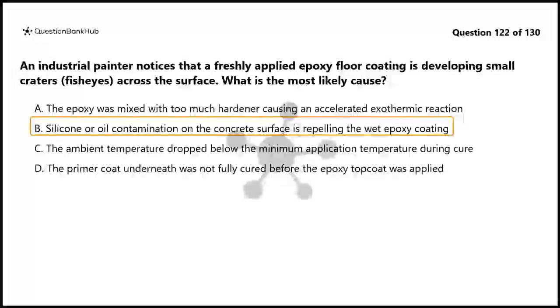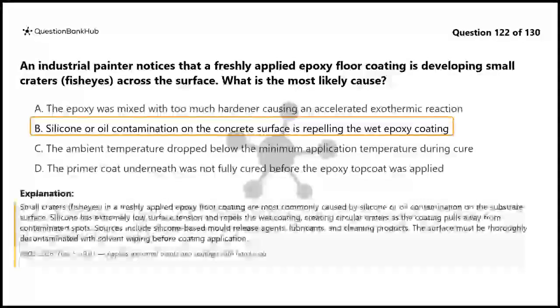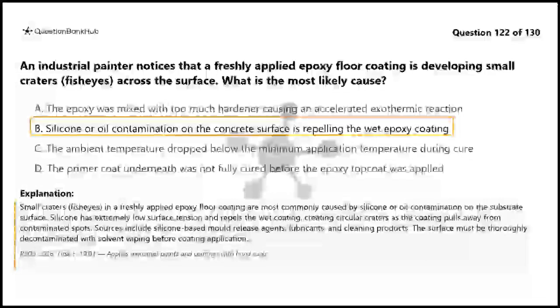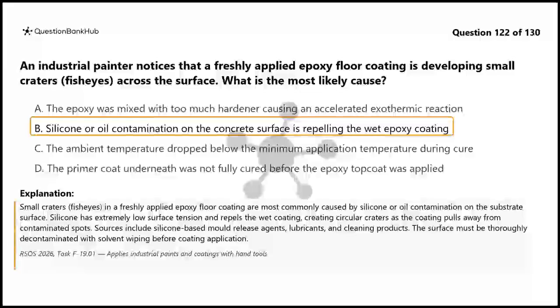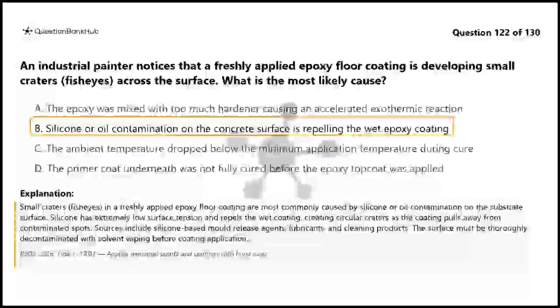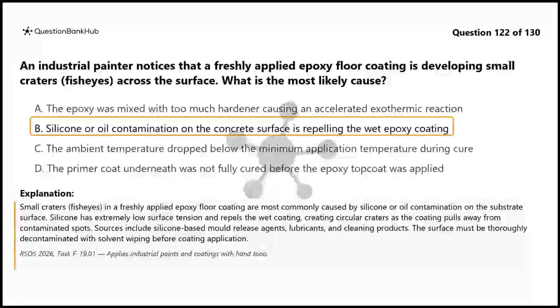The correct answer is B. Small craters, fisheyes, in a freshly applied epoxy floor coating are most commonly caused by silicone or oil contamination on the substrate surface. Silicone has extremely low surface tension and repels the wet coating, creating circular craters as the coating pulls away from contaminated spots. Sources include silicone-based mold release agents, lubricants, and cleaning products. The surface must be thoroughly decontaminated with solvent wiping before coating application.